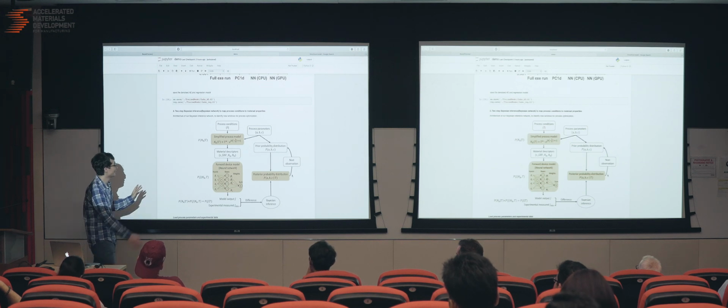The reason we need to speed this up is that when you perform the Bayesian inference, after we have the surrogate model, we are able to perform this hierarchical Bayes where you already have a neural network to map the material descriptors to the model output, and then you embed your physics knowledge, whereas you know that the MOCVD process is a kinetic process, and it should follow a certain type of Arrhenius equation relation.